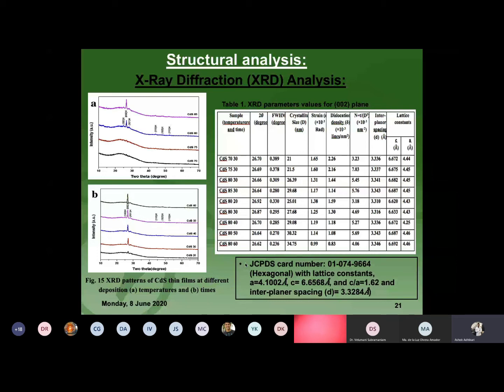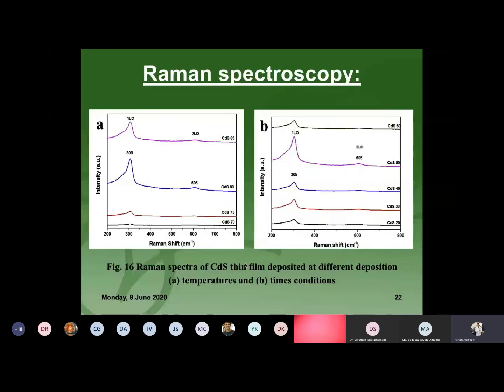For further structural characterization, I performed Raman spectroscopy. The first order longitudinal optical phonon mode was observed at 305 and the second at 605, resembling the hexagonal structure, which is also compatible with the results obtained from X-ray diffraction.